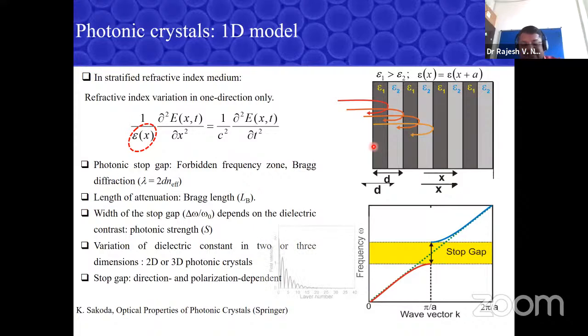If you look at the field in this system at these frequencies, this is a calculation I did. Take a frequency in this yellow region and look at the field intensity in the structure: you can see that it decays exponentially into the structure. This attenuation length we call the Bragg length of the system. It's not rocket science. In condensed matter, we have periodic atoms and X-ray diffraction. Similarly here, you go for optical diffraction, which you can see with your eyes. To achieve that, we need a periodic medium, and a condition like the Bragg condition from condensed matter physics, with slight modification, is also applicable here.